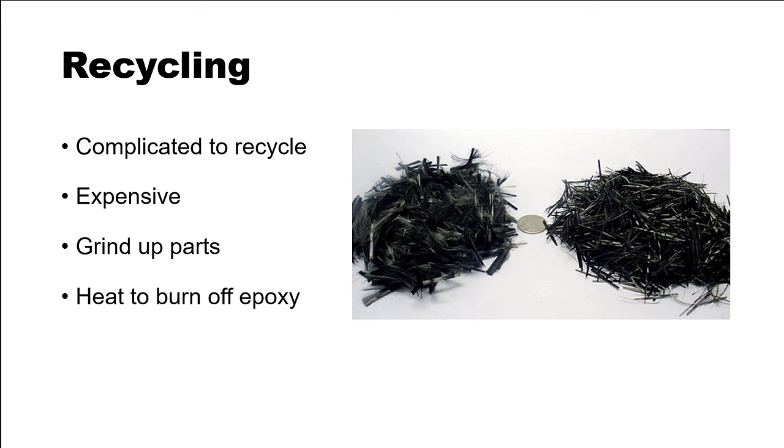So similar to how you would treat materials to make carbon fiber, you basically make it over again. So you heat it up without oxygen to burn off all the epoxy and all the other materials that are with it to just get the pure carbon back in the strands, which is what you see in the left pile. And that makes it to where you can apply it to new products and such to make it a new product all over again and fully recycle the material.